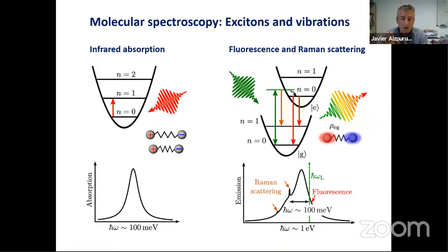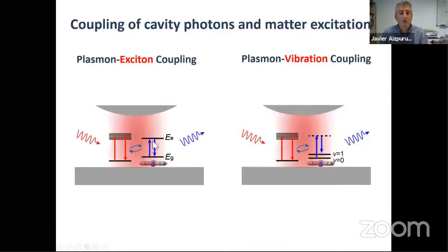It's hardly detectable for single molecules or for a few molecules. You need huge amounts of molecules to get some signal over the noise, recording this infrared absorption or this fluorescence or this Raman scattering. So in this context is where all I have just mentioned up to now comes in, these optical cavities, right? When we use plasmonic or metal-insulator-metal cavities, and we put our molecules in the middle of these metallic cavities, we improve the effective mode volume and therefore the interaction of the trapped photons with that molecule. We can do that with the excitons for fluorescence or with the vibrations in infrared or Raman, right?